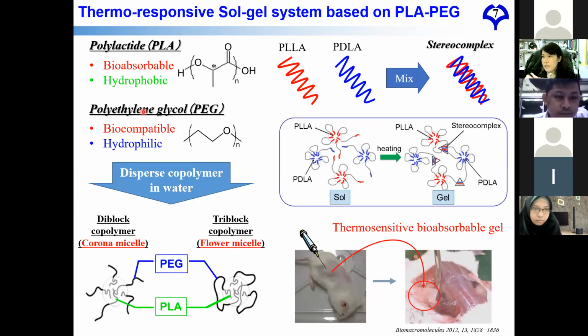As I mentioned before, PLA is hydrophobic. So how can we make this hydrophobic polymer into a hydrogel? First, we have to synthesize a copolymer with a hydrophilic segment. In this study, we use polyethylene glycol, PEG, to synthesize an amphiphilic copolymer. And we can disperse the copolymer into water. You can see here, the core is the hydrophobic PLA, and the shell has the hydrophilic PEG. The diblock copolymer of PLA and PEG forms a corona micelle.